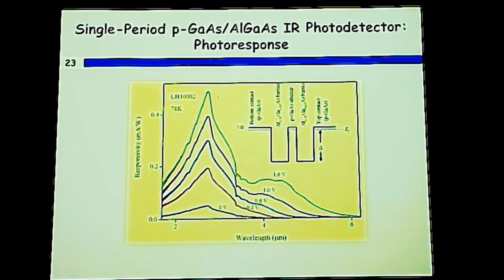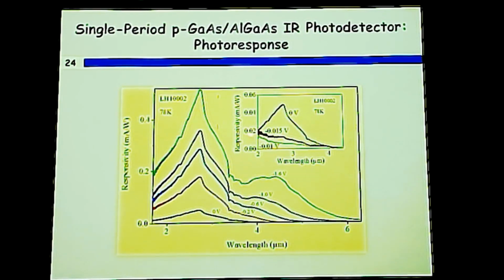In the negative, the negative bias tries to drive the carriers in the opposite direction. So at small negative biases, the photo response becomes weaker compared to that of zero volt, because there is a cancellation due to the opposite direction of the photo current. With a slightly increased bias, the photo response in the negative slightly increases. With further increase, it becomes stronger in the other direction.